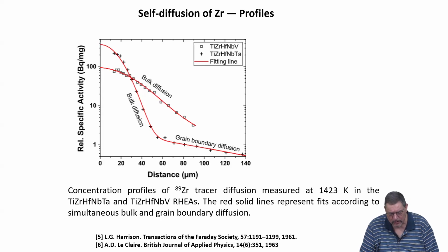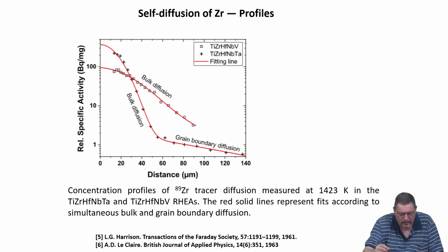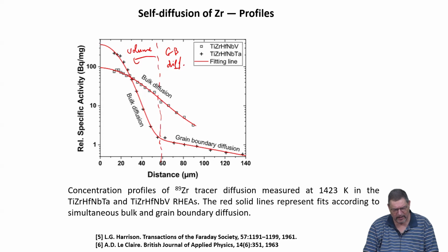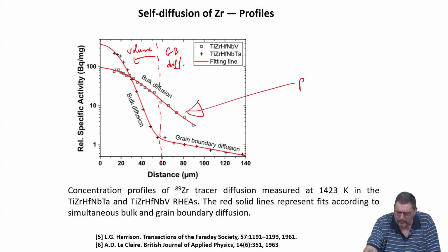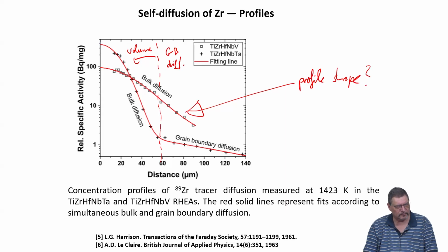So you see here, as a function of normal distance, these penetration profiles, and you see them for the two alloys marked by either crosses or squares. And you typically see that for the crosses, the tantalum-containing alloy, you have a nice demarcation between volume and grain boundary diffusion. For the vanadium-containing system, that is not so obvious, right? What would you think of the profile shape here? It is mostly grain boundary, exactly, yes.